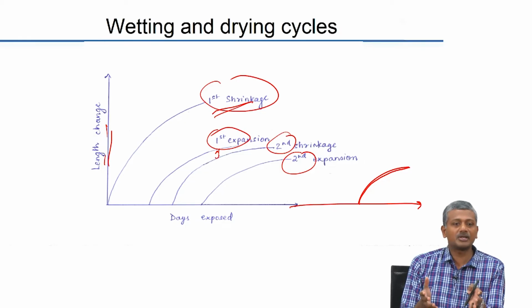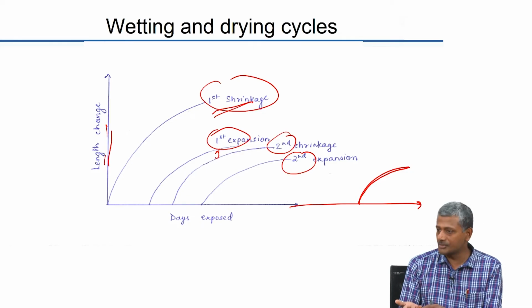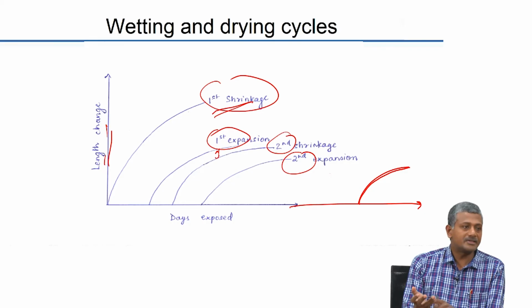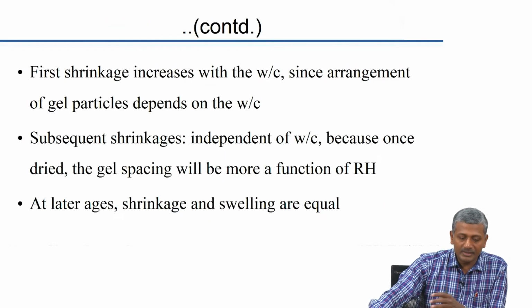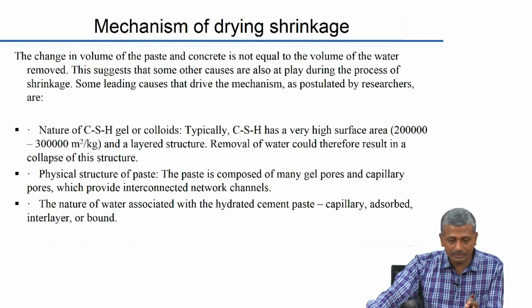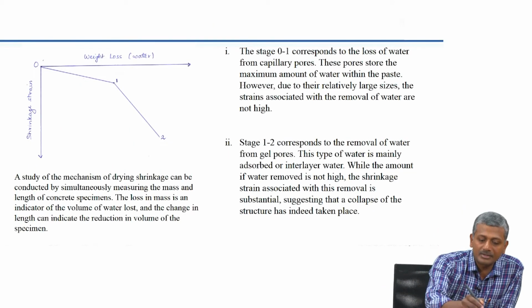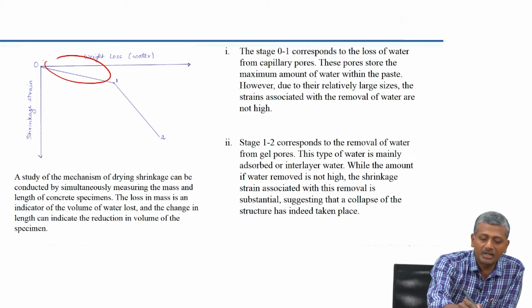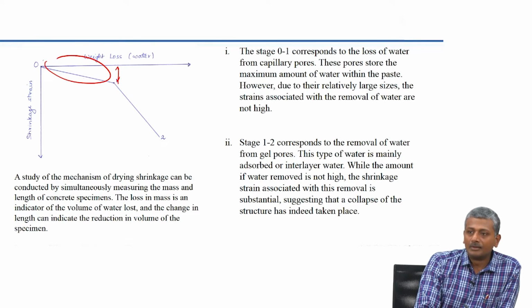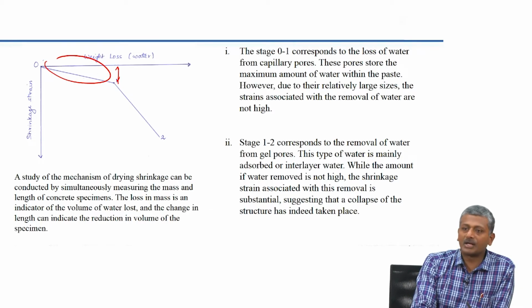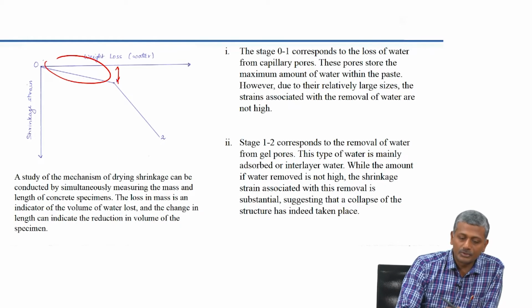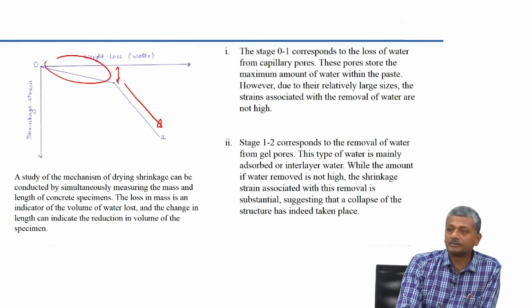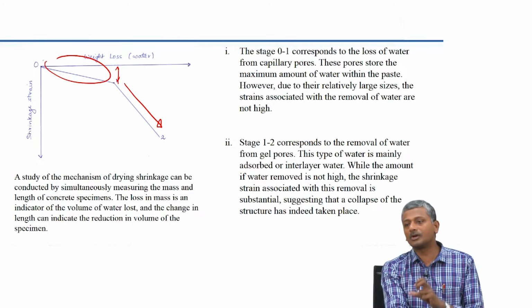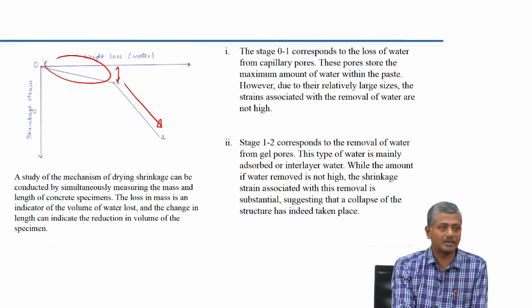But if your system is saturated, a lot of water may be there in your coarse capillary pores. So, if you measure the weight loss along with your length change, you might see an interesting trend. The weight loss is very high in the beginning, but the shrinkage strain is quite small. That is because you are pulling the water out of the coarser pores. But once you overcome that and you start pulling out the water from the finer pores, the extent of shrinkage goes up very rapidly, but the extent of water loss does not change significantly for the same extent of shrinkage.